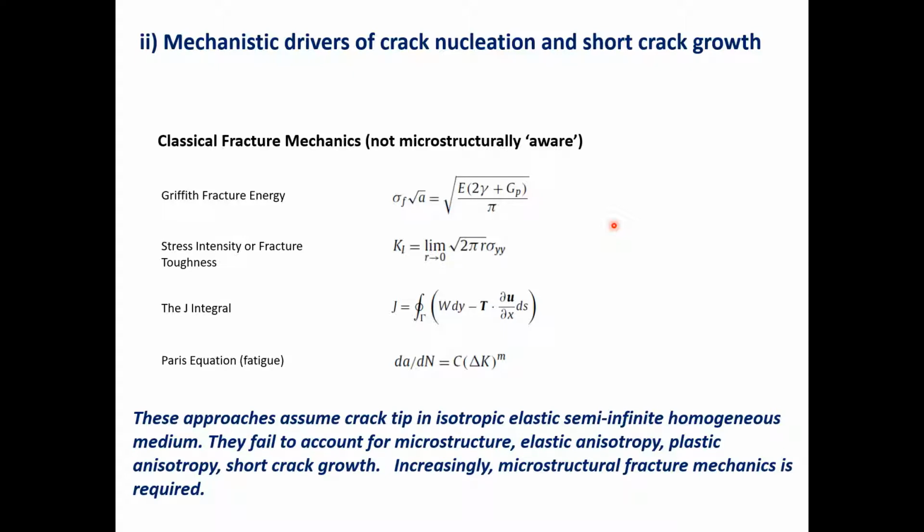the microstructural information. The one method that incorporates plasticity in any detailed way is the J integral, of course, but also suffers from the same sorts of continuum problems and the absence of representation of microstructure. And then Paris law, of course, which is for crack growth, is related to delta K, so therefore has the same issues associated with the stress intensity. So there are a whole range of issues with these methods that don't immediately make them obvious for looking at the understanding of microstructure-sensitive crack nucleation, or particularly growth.